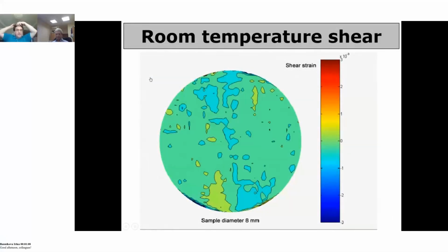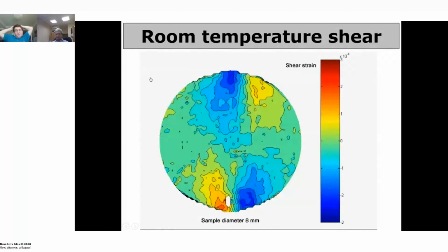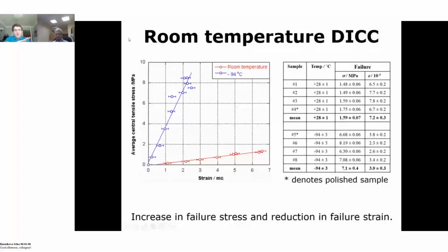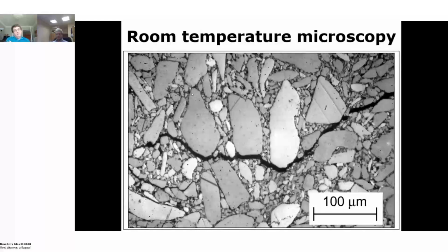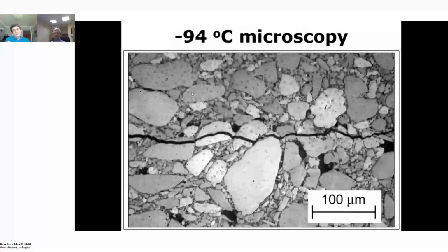Now you can see that this is not as nice, not as perfect as the calculation, and I fully agree. So here we have the room temperature response of that material versus the -94 response. You see below that glass transition temperature, you can see the increased strength in the system, the catastrophic failure. And when you look at the failure in this granular composite in detail, you see these cracks going kind of around things there quite clearly. And when you do that at -94, well, that crack just goes straight through the